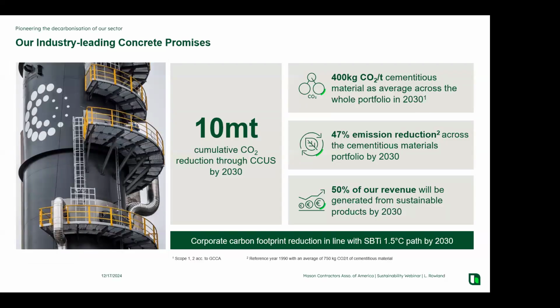So as a cement producer and as a company that's very much dedicated to decarbonizing the industry, we have adopted very aggressive carbon reduction goals. And we've broken them out. The amount of carbon, according to our cementitious materials, instead of 900, we're trying to get down to 400 kilograms per ton of cementitious materials. This is going to be everything from Portland cements, Portland limestone cements, supplementary cementitious materials. The total production worldwide, we're targeting getting down to 400 kg. And as explained, that is much less than even the calcination emissions associated with making Portland cement. So this is a real heavy lift, and we're making it happen.